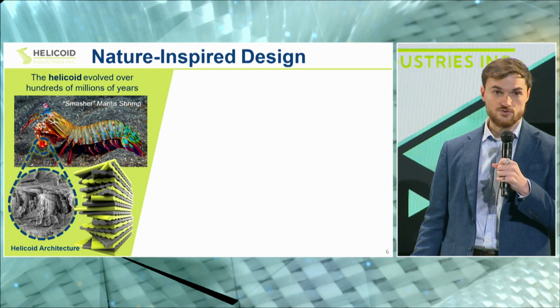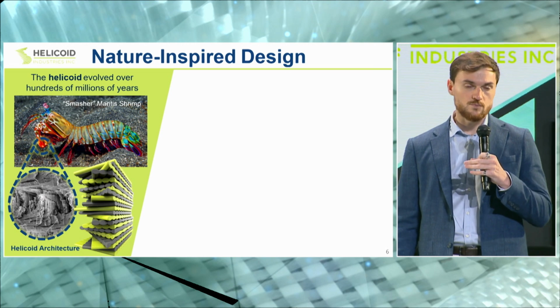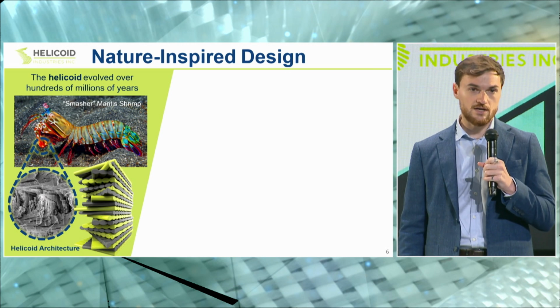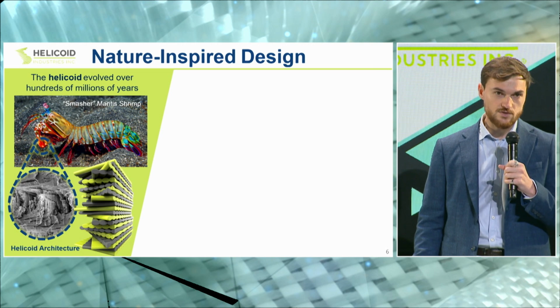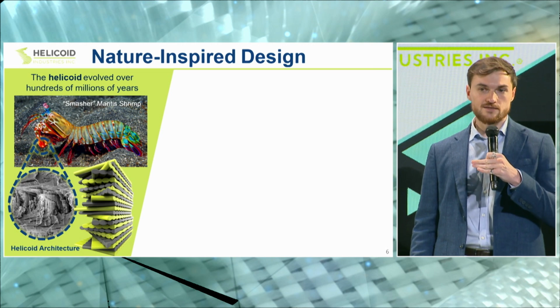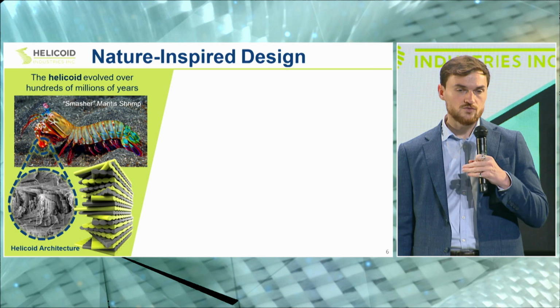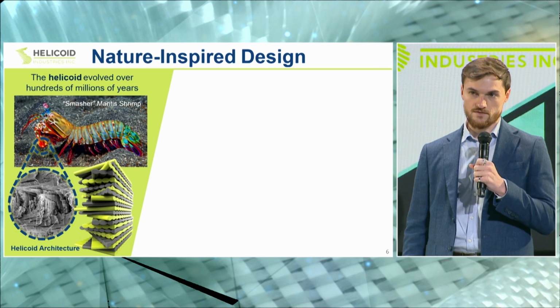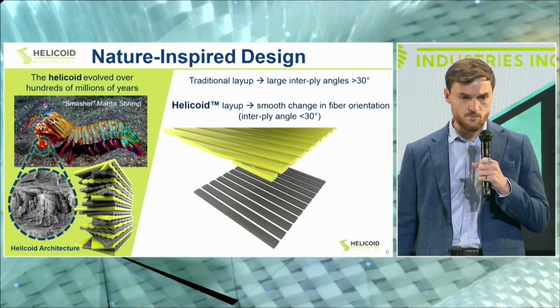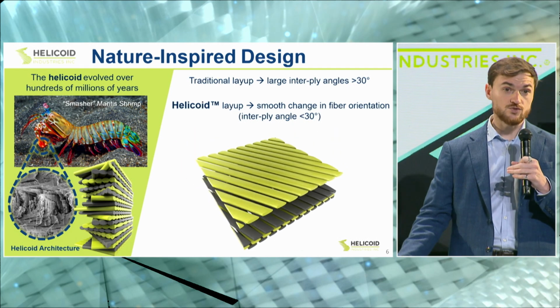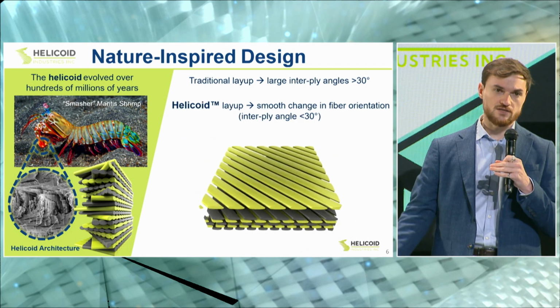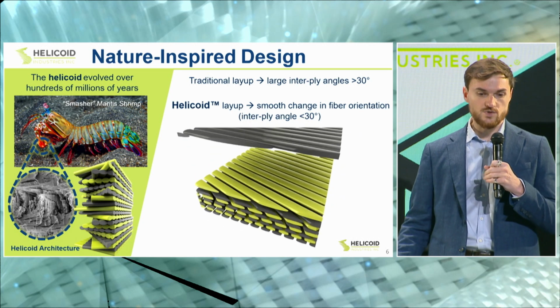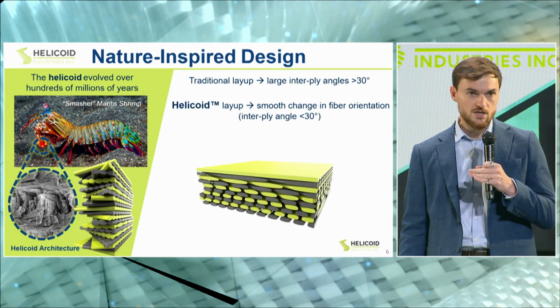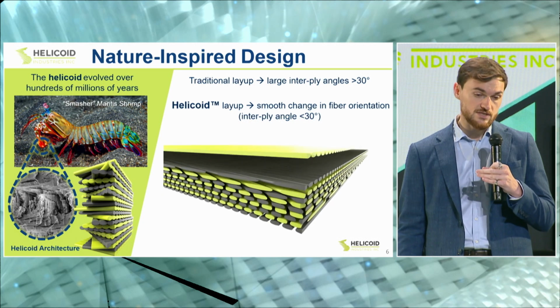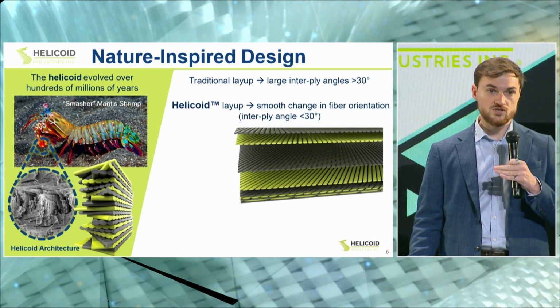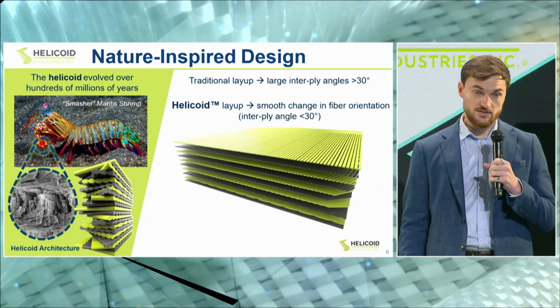If you look inside the microstructure, you will see that is composed by UD layers, very similar to a conventional laminate design that we use today in engineering, which are slightly rotated one to respect to each other to form this helicoidal distribution of fibers. So compared to a traditional layup where we tend to use large interply angles, larger than 30 degrees usually, in helicoid we smooth the change in fiber orientation with angles lower than 30 degrees. And we also use blocks of traditional layup to tailor stiffness and strength of the laminate.